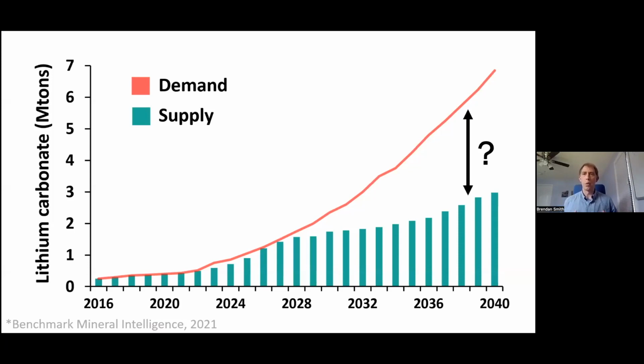And so just to put some numbers behind this, this figure looks namely at lithium carbonate, along with lithium hydroxide, the key lithium compound in battery manufacturing. What we see here is a projection from Benchmark Mineral Intelligence, kind of the key mineral forecasting agency. And we can see that the demand is projected to outstrip supply by about 150 or 200% as soon as 2040. And in fact, the shortages are supposed to start much earlier than that, as per these projections. Nickel and cobalt have similar supply constrictions forecast into the future.